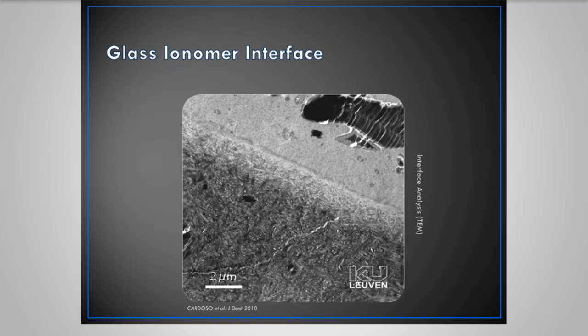And as I mentioned, the glass ionomer has an acid-base resistant zone. You'll notice here the glass ionomer in this area, the natural tooth down here. This is where the tooth structure's original surface was, this kind of grayish line. You'll notice from this gray line to this kind of diffuse area here is this glass ionomer acid-base resistant zone. So material has actually impregnated from the glass ionomer into the tooth, creating this layer. This acid-base resistant zone is hypermineralized dentin that, should this glass ionomer, let's say, fail all the way down to where the tooth structure is, is actually hypermineralized and more resistant to acid attack from bacteria and more resistant to decay than traditional dentin that never had exposure to glass ionomer.